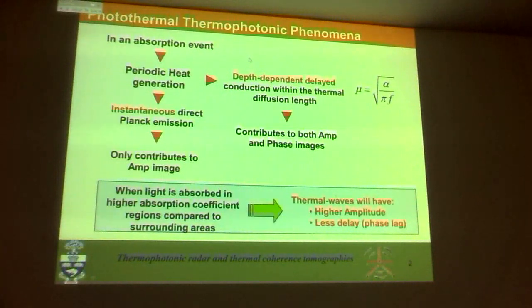So the important thing about heat is that ultimately it is a component that is missing from photoacoustics. What is not converted into acoustic energy is converted into heat. There are other conversion channels. One of them is just light into light, optical to optical transfer. So when it comes down to photothermal detection, you always have an efficiency, a non-radiative quantum efficiency. How much of the light is converted into heat? If 100% is converted to heat, your efficiency coefficient eta is equal to 1. If less than that, then you get less and less.